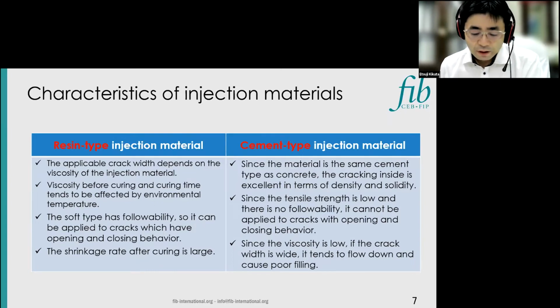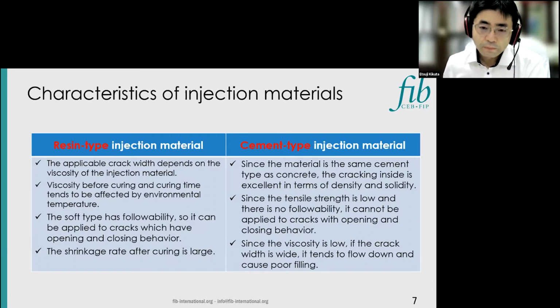The cement type is the same material as the structure to be repaired. And the crack inside is excellent in terms of density and solidity. But since the tensile strength is low and there is no flexibility, it cannot be applied to cracks with opening and closing behavior. In addition, since the viscosity is low, if the crack width is large, it tends to fall down and cause poor filling.